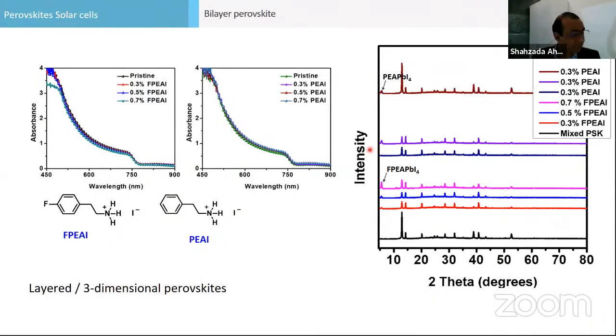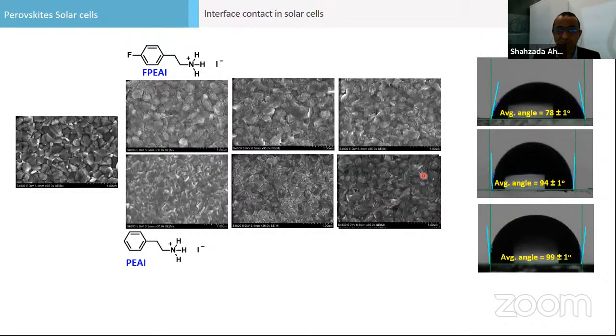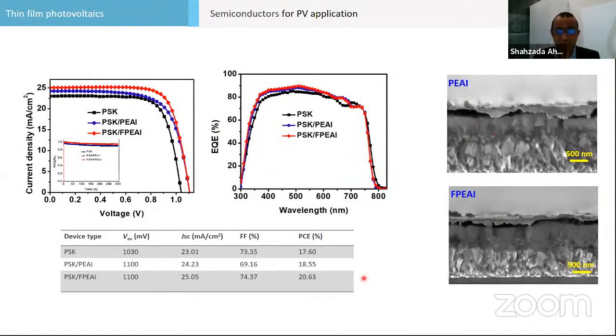I will go a little bit faster now because we are behind schedule. We are now studying a bilayer type of structure, 2D and 3D. And we found that this bilayer structure increases stability to a larger extent. So this is a PEAI, these are fluorinated molecules. And we all know that fluorinated molecules have a higher surface tension and are better for increasing stability. The contact angle has also increased in the 2D molecule with fluorinated, and this becomes a more stable perovskite, protecting the layers. And we have achieved almost 21% efficiency with the bilayer perovskite, but much higher stability with that one.